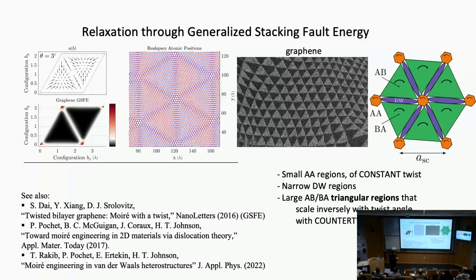And these very narrow, hexagonal or almost circular regions, here you see them in the theory. In experiment, again, you don't see them. They're tiny. And these are the so-called AA regions, which are the high energy regions. And these are the low energy regions. So basically, the system tries to create as large triangles as possible because they correspond to the optimal stacking of the layers. But because of the overall imposed relative twist, you cannot avoid having domain walls between these triangles and these corner regions, which are the so-called AA regions.